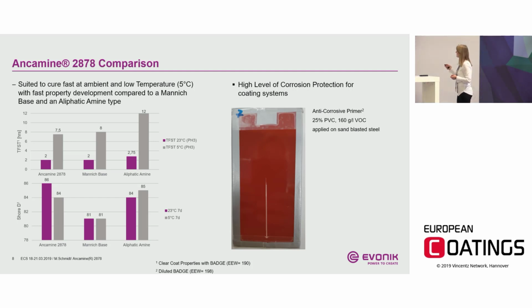Comparing Ancamine 2878 with an aliphatic amine, you can see here on low temperature cure, it's not directly comparable, but the aliphatic amine is not so fast, and our Ancamine 2878 is much faster, also at low temperature cure, which is what we want. We also compared the Shore D hardness, as seen from Ancamine 2878 before. We have a relatively high Shore D hardness after 7 days at room temperature and low temperature. When you compare it to the aliphatic amine, it's relatively comparable, but with the Mannich base you have a little bit less Shore D hardness.